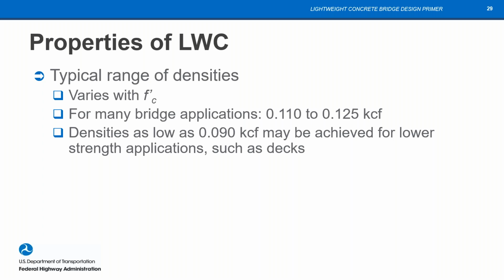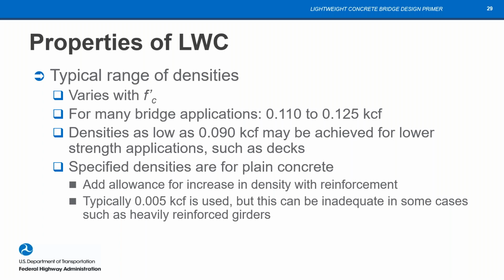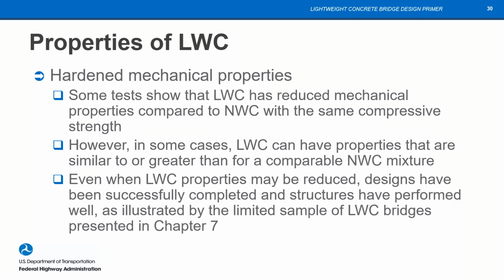But the strength of lightweight tends to be a little bit more sensitive to the change of densities. You can get down into the 95 or 90 pounds a cubic foot range with an all lightweight mix. And also that would include air. We're using air to reduce the density also. And that's how we get to the lowest densities, was with all lightweight. Then we have to add an allowance for increase in density with reinforcement, which is typical for normal weight concrete